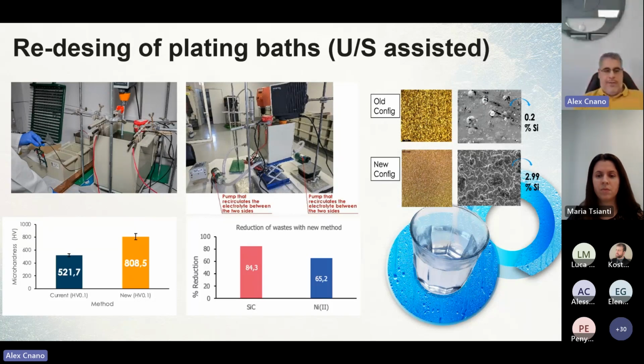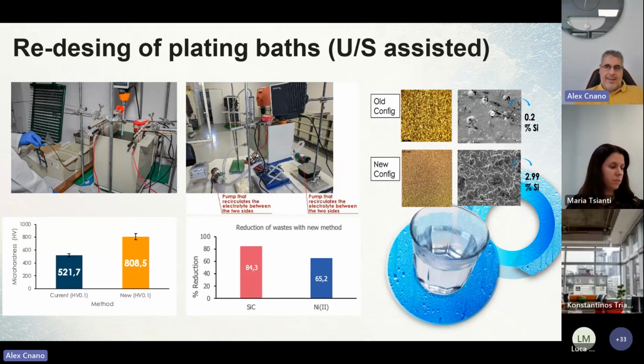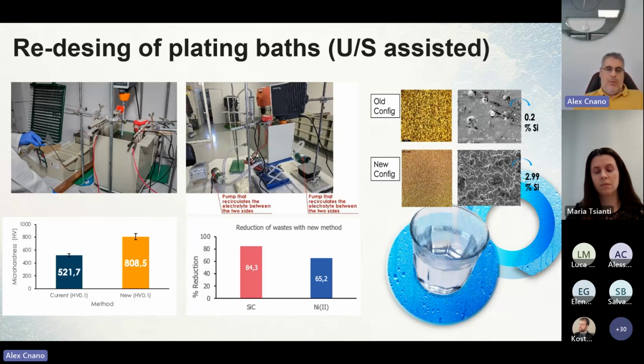So here, this is a combination of the Sabidoma and Mozart project. You can see how we can shift from a single tank bath to two tanks that are connected, in which we can apply ultrasonication so as to increase the dispersibility of the particles inside the solution and to achieve better coatings. It is characteristic that with the traditional one tank bath, we can achieve under the same plating conditions coatings that will have 0.2% silicon carbide with a very bad distribution, versus coatings that can reach 3% of silicon carbide with an excellent distribution.